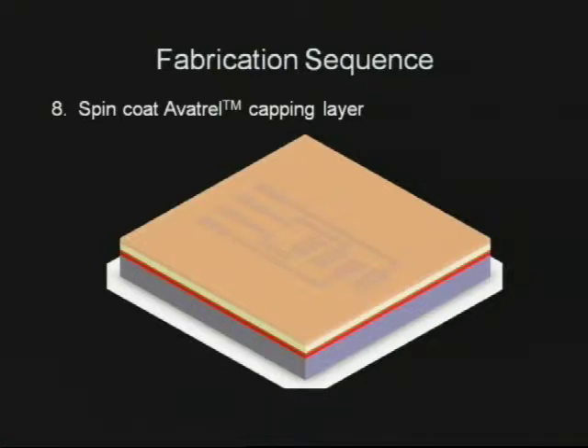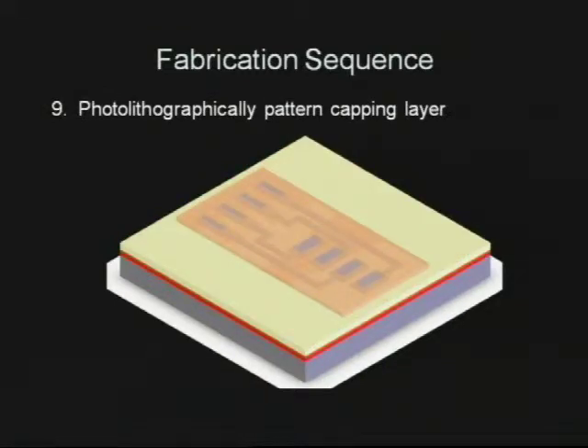So we use a novel spin-castable photodefinable polymer that's actually developed by a company here in Northeast Ohio called Avatrel. It's a polynorbornene. We put that on as a thin layer, roughly 5 to 10 microns. Then we're able to photolithographically pattern it. It's now opening windows to the metal electrodes and contact pads and exposing large areas of the